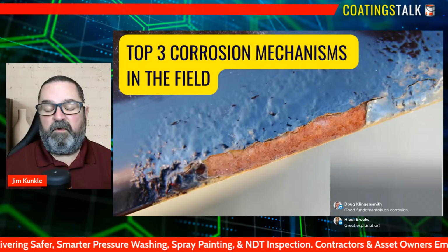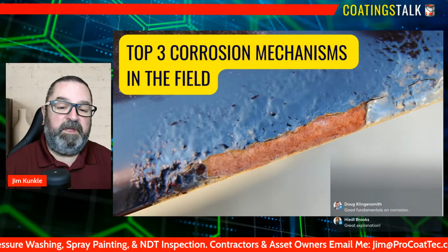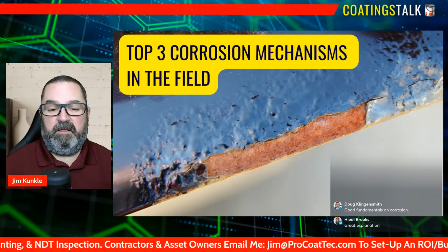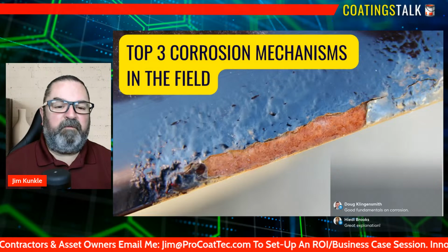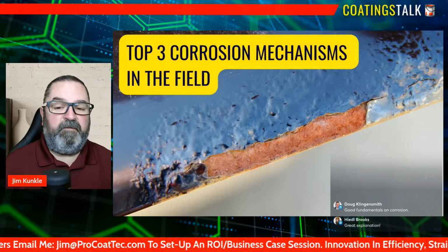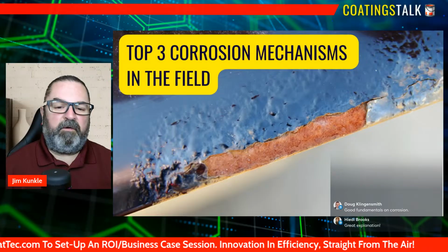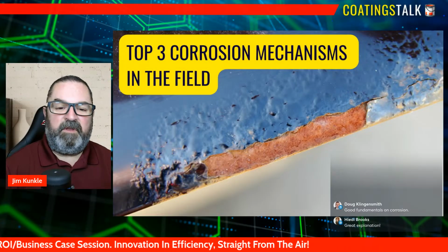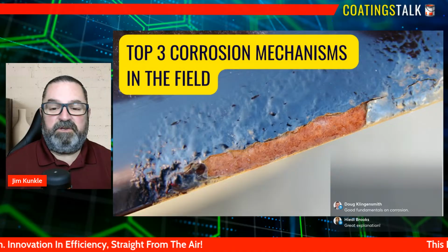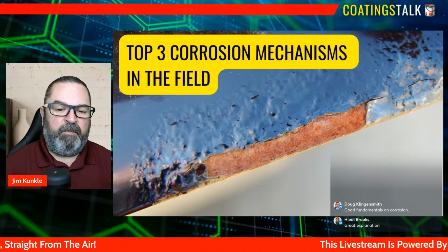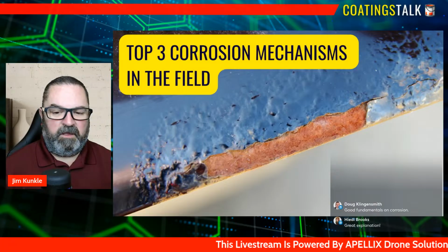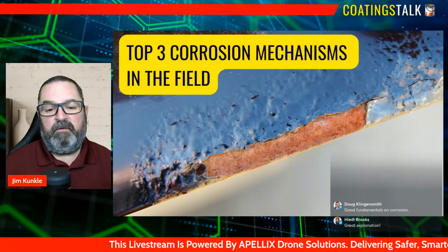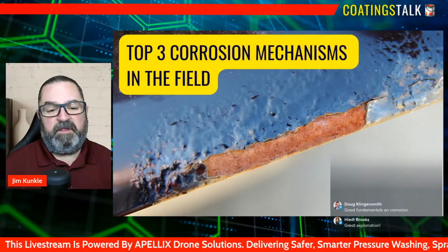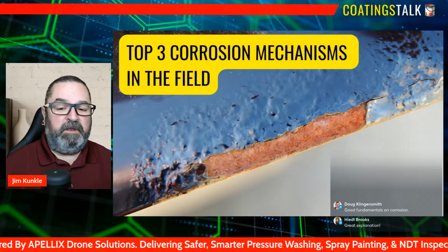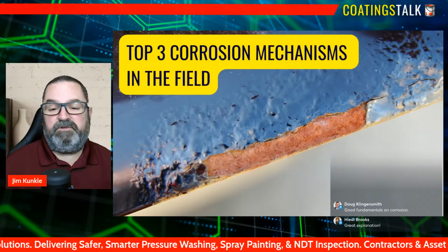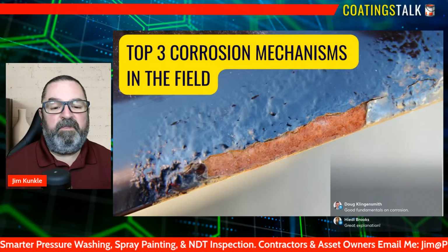The next form of corrosion I want to talk about is galvanic corrosion, and this is dissimilar metals in contact. Galvanic corrosion is one of the most common and most avoidable corrosion mechanisms encountered in the field. It occurs when two dissimilar metals come into direct contact in the presence of an electrolyte, such as moisture, condensation, or salt water. In that moment, the metals form a tiny electrical circuit. One metal becomes the anode, and corrodes faster than it would on its own, while the other becomes a cathode and is protected.